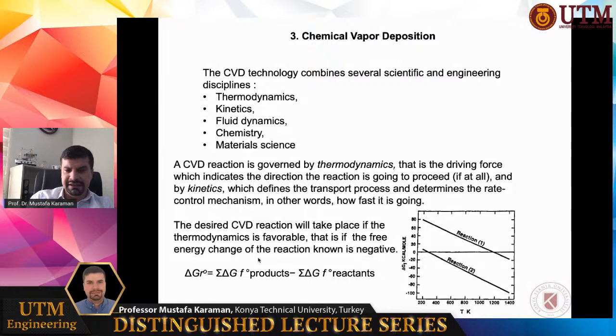And second, chemical kinetics, which defines the transport processes and determines the rate controlling mechanism. In other words, how fast it is going, how fast the deposition rates are. The deposition rates are determined from chemical kinetics. But if a deposition will occur or not, it will be determined from thermodynamics. There are many different analyses.